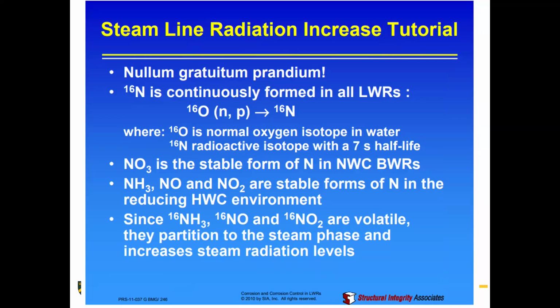This is for nitrogen-16. Normally under normal water chemistry, this nitrogen-16 would be stable in the form of nitrate. It would form some kind of deposit, some kind of stable product within the actual circuit. But once you switch to hydrogen chemistry, you're then going to form ammonia or a nitric oxide. At this point, nitrite, I think, these are going to end up being volatile and they're going to pass over to your steam turbine. And again, nitrogen-16 is radioactive, and so you will start to dose your workers.